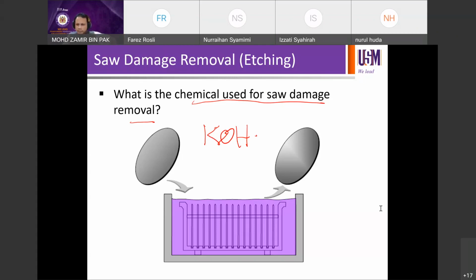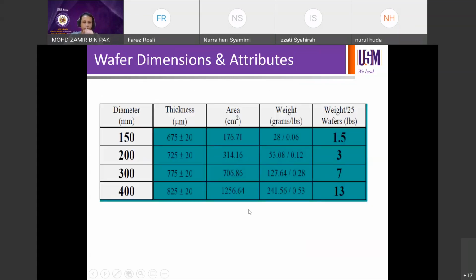Tima, okay, Tima: hydrofluoric, HF, and nitric, sodium hydroxide. Most alkaline can be used. Yep, all right, the common one is you can use either KOH or NaOH. Both are alkaline solutions. So potassium hydroxide, well, you can also use TMAH. TMAH is also alkaline. But the most common ones are KOH and NaOH. Okay, sodium hydroxide, potassium hydroxide. You can also use TMAH with high concentration.